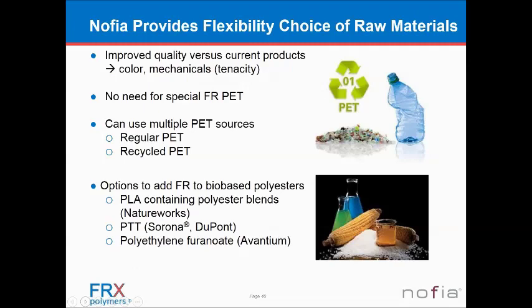With our material, apart from that, we typically give an improvement in terms of color. So when our material is being used, you can make a wider fiber. You also have better mechanicals, so a higher tenacity, but you don't need the special flame retardant polyester. So the downstream users have a big advantage that they don't need to use a specific flame retardant PET, but they can use their own PET that they use for their regular spinning of fibers. And they can just switch their downstream equipment and add a small stream of our material into the PET.